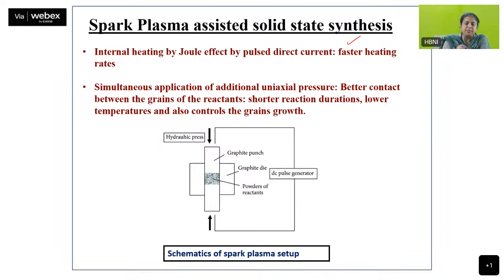So what is this? Spark plasma involves simultaneous application of high current and pressure. Internal heating happens by Joule's effect by direct current, and it has a faster heating rate. Simultaneously, you apply a uniaxial pressure. This results in better contact between the grains, shorter reaction duration, lower temperature, and also, as I mentioned, it controls the grain growth.